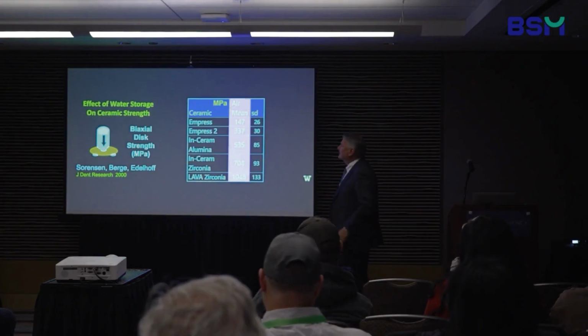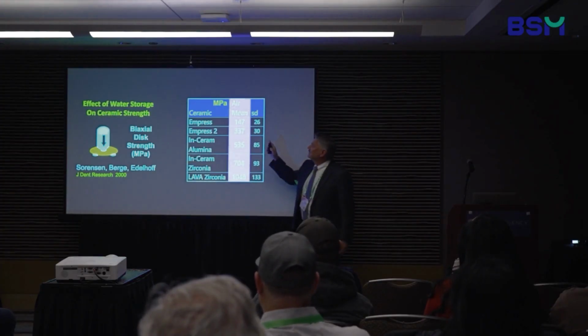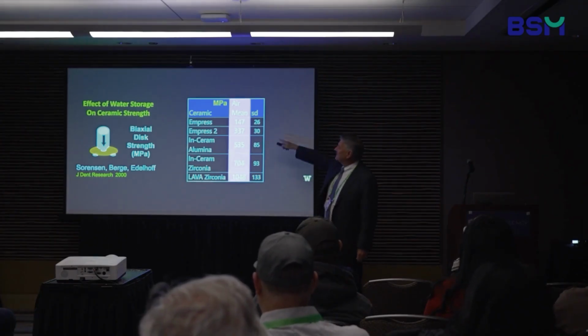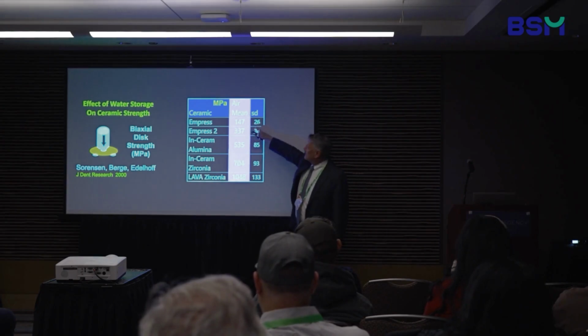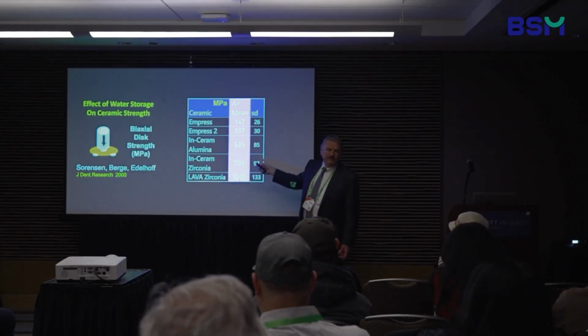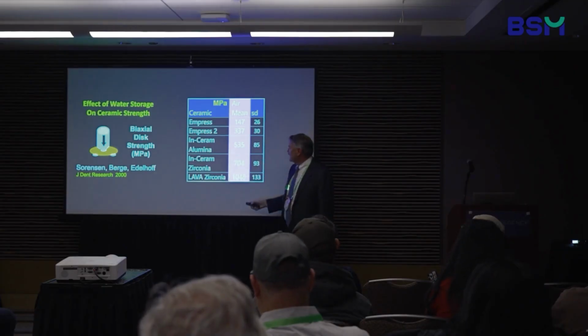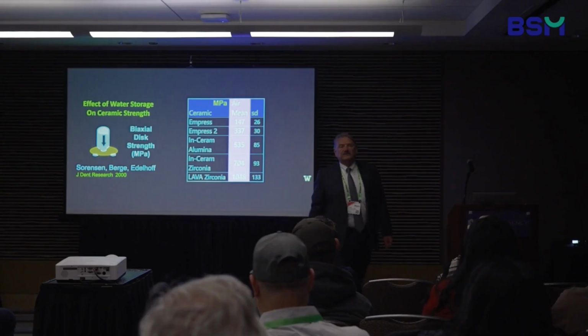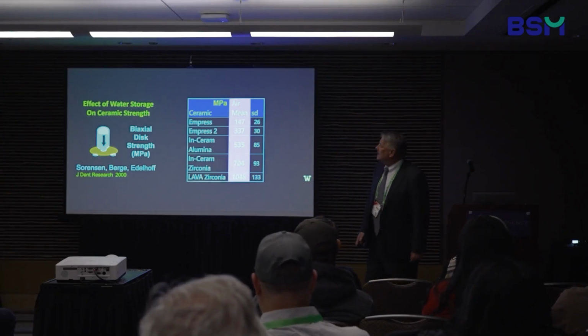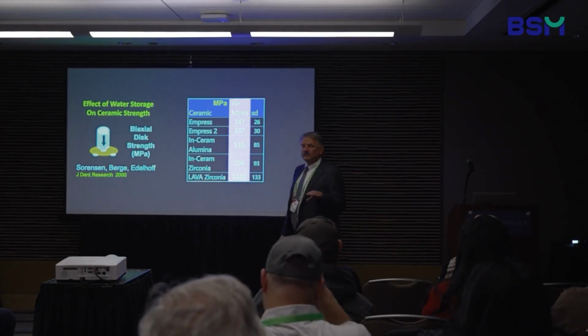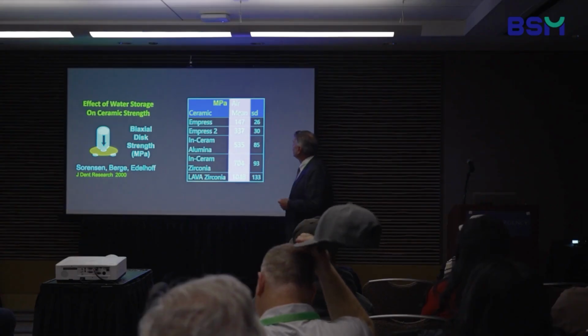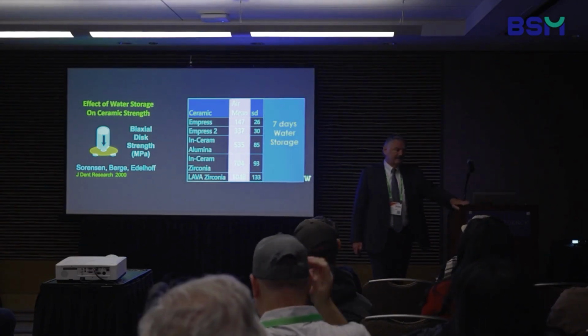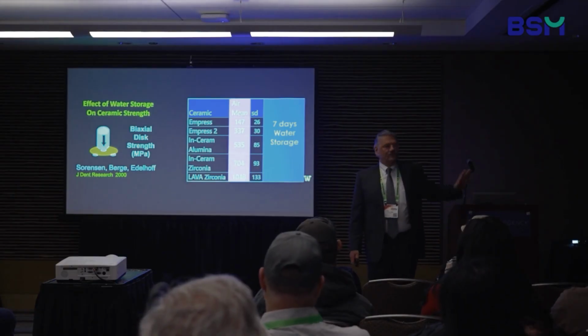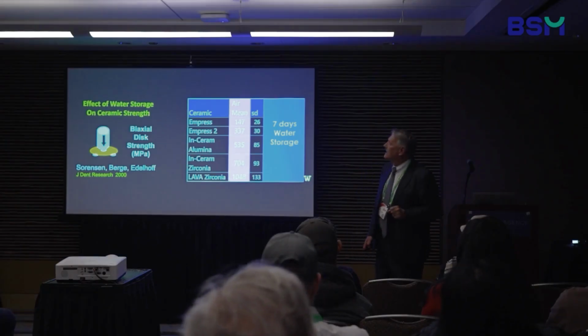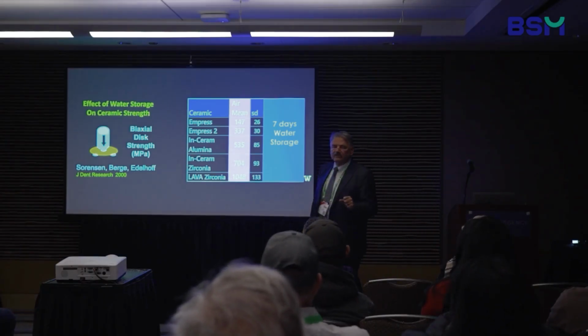When Daniel was on sabbatical with me, we did a little study and looked at the flexural strength of the basic systems that were out there. You can see pretty typical values for Empress 2, In-Ceram, In-Ceram Zirconia, which was about 40% zirconia, and then Lava zirconia. Wow, that knocked our socks off, over 1,000 megapascals. We then took a group of samples and stored them in water for 7 days. In the mouth, functioning, we're in saliva all the time, with the breakdown that goes on in the ceramic structure with that.